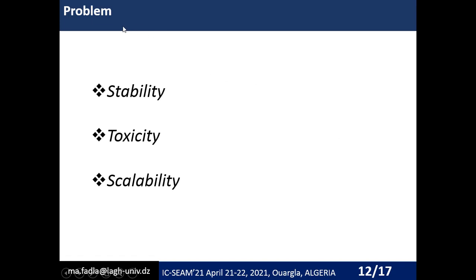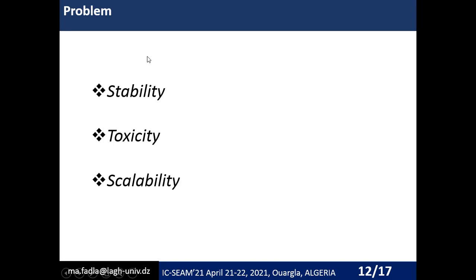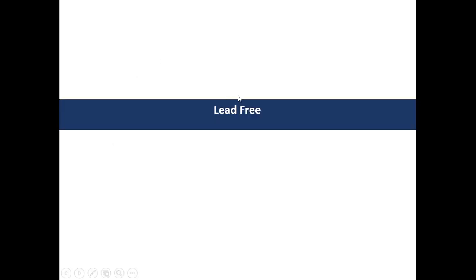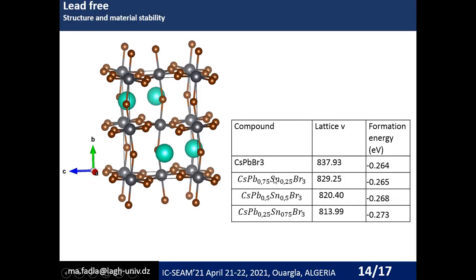So what is the problem that limits the commercialization of perovskite material? The first is the stability. These compounds are not stable under ambient conditions or temperature and can be decomposed with toxic elements. The second is the toxicity of this compound, as they contain the lead atom, and the scalability. Therefore, to resolve these two parameters, stability and toxicity, we use the tin atom and substitute the toxic lead atom.